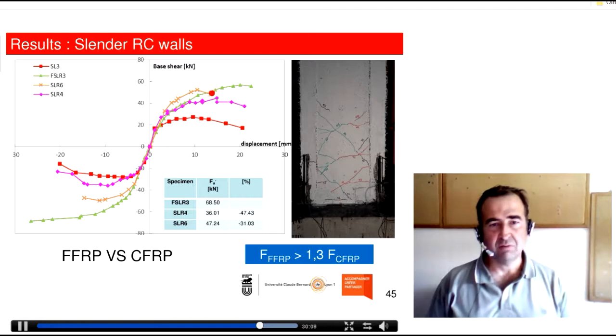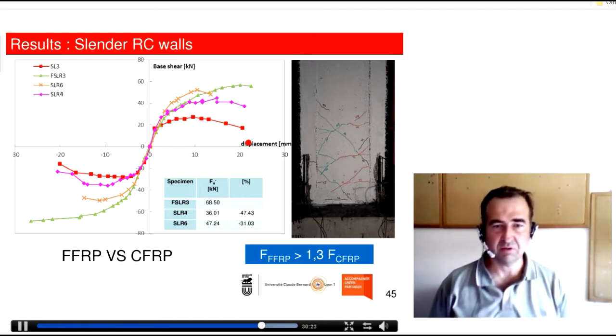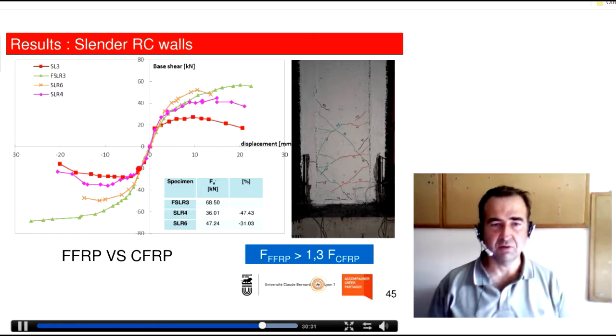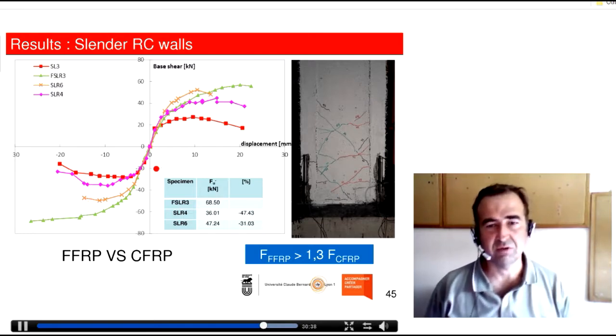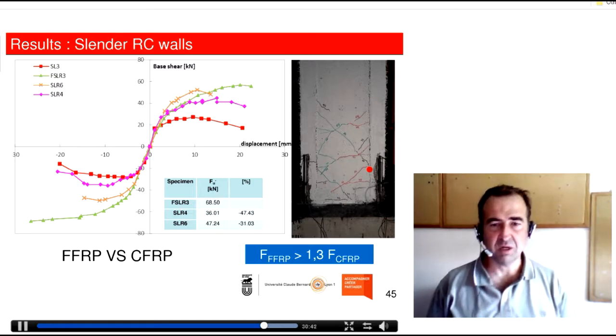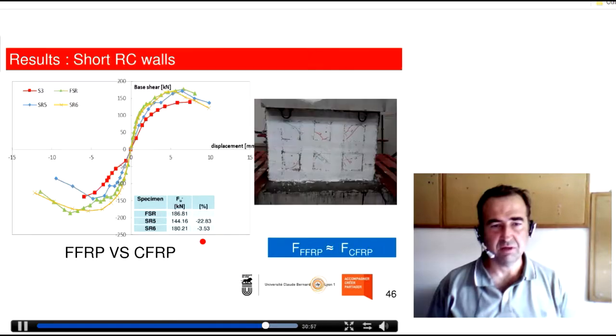Then to compare with carbon, as I mentioned, you can observe that the carbon wall was here, and the one in green was the one strengthened by flax fibers. What you can see is that it's very interesting since we have an important increase in load, but also in displacement capacity, in compression and in tension, because we have push and pull tests. So the test is very nice, and much nicer than the one obtained with carbon. In the carbon test, we have some buckling of the carbon due to the important Young modulus of the carbon. In this specimen, the debonding did not occur, and we have very nice behavior until the failure. So this is the comparison for shear failure.